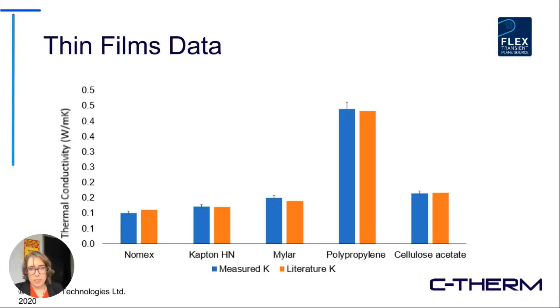So we've collected a variety of data on various thin films that are commercially available that you can see on this slide. In all cases, our agreement with the literature values for these materials is better than 5%.